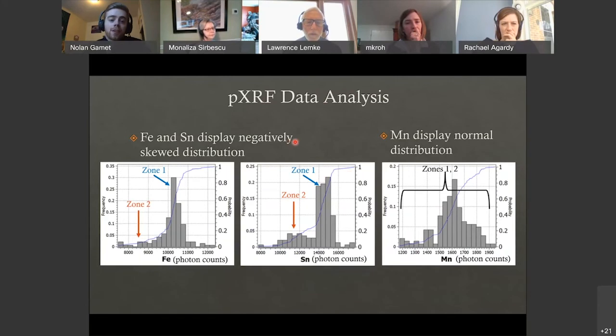Furthermore, we constructed histograms which showed that iron and tin had more negatively skewed distributions, in which we then determined that zone 2 had the lower counts and zone 1 had the higher counts, as seen in iron and tin. And then manganese was more of a normal or Gaussian distribution, and it was harder to determine the zone differentiation because it was more randomly spread around the crystal.